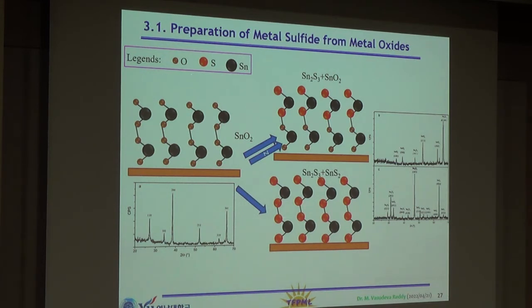Here the legends indicate the colors for oxygen, sulfur and tin. We thought the tin oxide would be replaced, and we did several experiments at different temperatures, time periods and pressures. But still it is not close to forming tin monosulfide. We obtained either tin oxide with tin sesquisulfide or tin disulfide with tin sesquisulfide, but we intended to develop tin monosulfide for solar cell application.